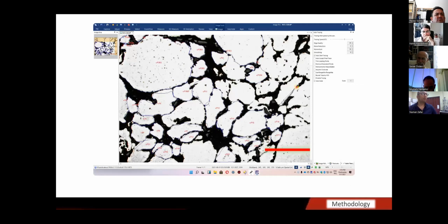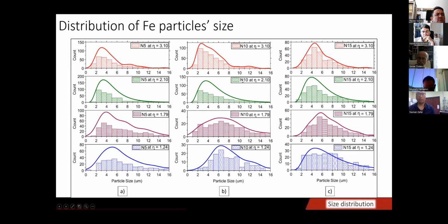And I also used that to measure the distribution of iron particles at different deformation levels and at different reinforcement ratios. N5, N10, and N15 show the influence of reinforcement ratios on the co-deformation behavior of the iron particles, going from the lower image to the upper image. You see increasing deformation levels. What we see is there is a fair distribution of iron particle sizes, but when you go to the higher deformation levels, the distribution is shifted towards the left side. Left, yes. So it means that a large fraction of iron particles belongs to the smaller size iron particles.